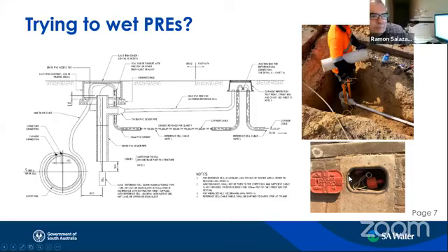So one of the things is thinking about reactivating the reference electrode if it's in the middle of the road. One of the contractors did this following installation. Because the reference electrode is under the road, you have this road chamber, but you don't have access to that, because you will need to set up traffic management. So then you had to bring the reference electrode to the footpath. So they came up with installing a PVC pipe going from the test point on the footpath to wet the reference electrode. So basically you come from the road, for example, this photo at the bottom. You see the open PVC pipe. So you pour water in and you could reactivate the reference electrode.